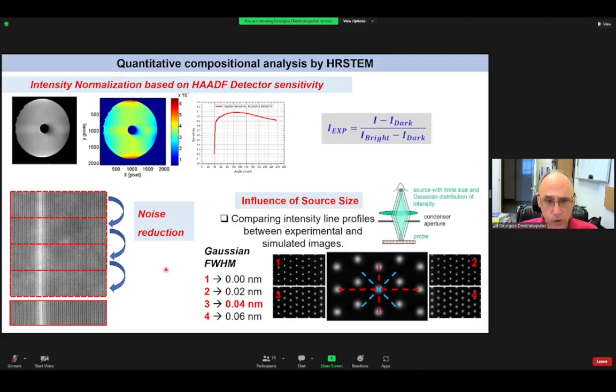You also need to know the thickness of your sample, which Isaac will tell you a bit more about, and also you need to know the source size, the size of your probe, so you can use image simulations and compare the atomic column that you are observing. So you have to scan your atomic column along various directions and obtain the Gaussian. And from the full width half maximum of the Gaussian, you can define the source size. And you need this in order to be able to choose the appropriate image simulation that you are going to use.